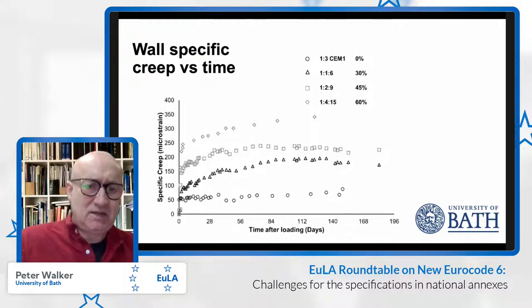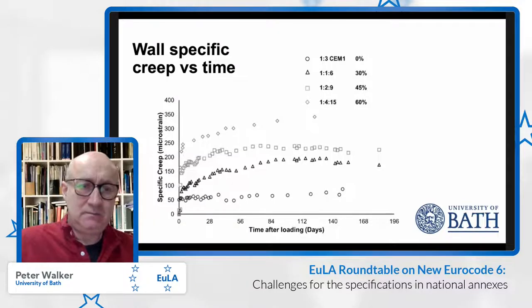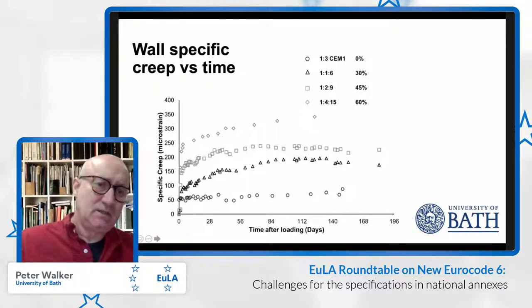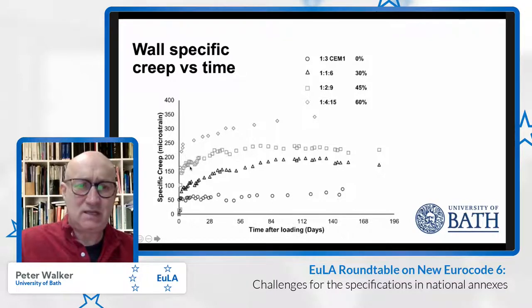This graph here presents one of numerous tests. We did a series of tests. I think overall 16 walls were subject to creep testing. So this is specific creep, although in this case, all of the walls were tested at the same vertical stress of 2 newton per square millimeter, and shows the average creep measured over a 6 month period